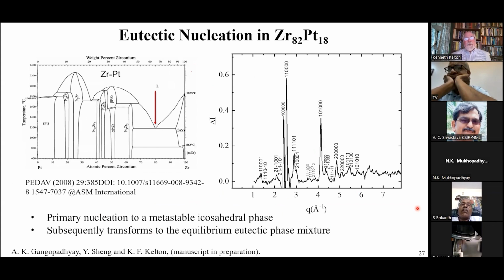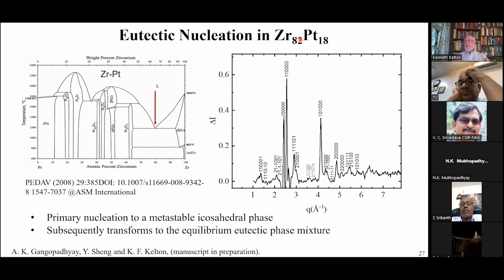Okay. Now, the other thing is much more recent data that we've just finished, and we have a manuscript in preparation for publication. We looked at the eutectic nucleation of zirconium-82 platinum-18. That's right here. Why did we do that? Well, if you go to the literature, and I didn't know this until about a year ago, and try to see what we know about eutectic nucleation, you find there's virtually nothing in the literature. We understand quite well eutectic growth. We teach that in our graduate kinetics classes. But nucleation, nobody has done any experiments on it.